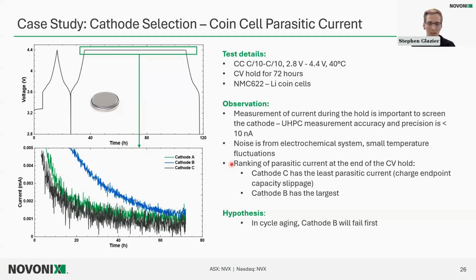So we have cathode A, B, and C, and right away upon receiving these materials, very quickly we can turn around some coin cells, and instead of cycling these and trying to tease out some cycle data, we put them through this kind of stress test on UHPC where we did a constant voltage hold and teased out parasitic current, the current needed to, once all of the kinetics have equilibrated within the cell, maintain that voltage for these materials. And this rate of this current that we collect is essentially analogous to the rate of electrons we're stripping out of some things like the electrolyte or related to transition metal dissolution in the cell, electron donating reactions that are showing higher reactivity from these cathode materials, and basically measuring those directly.